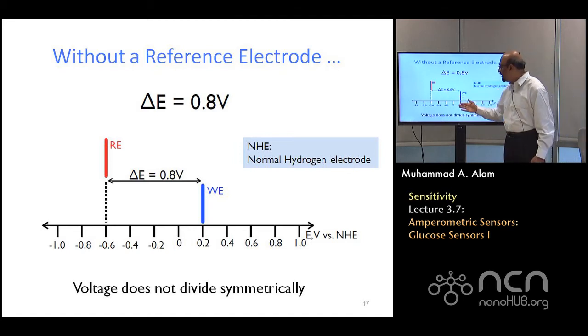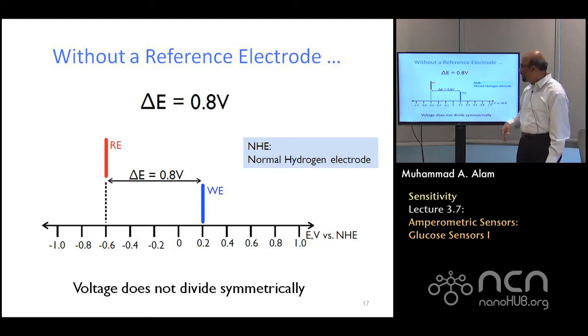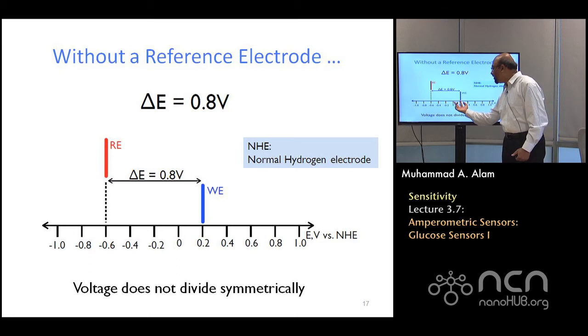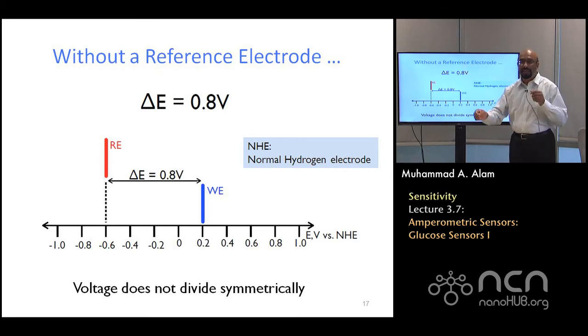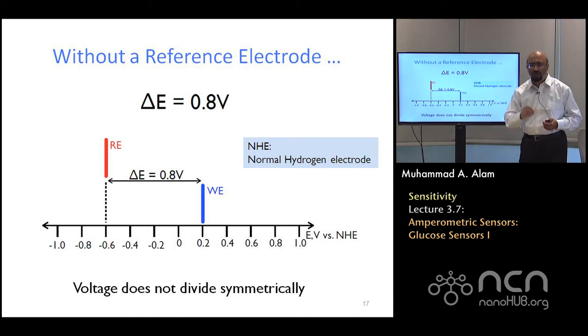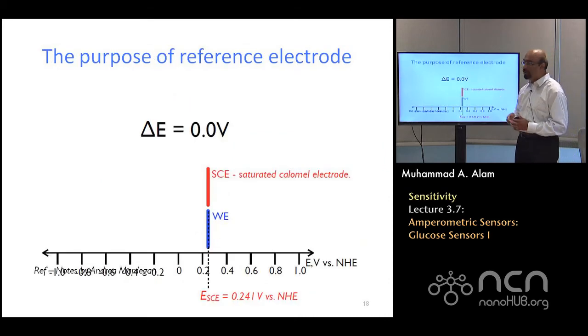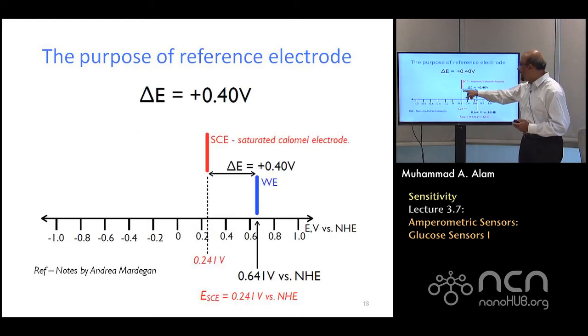The reason is that if, in this particular case, I apply 0.8 volts rather than 350 millivolts, then I cannot say a priori what fraction will get onto the working electrode and what fraction will get to the other electrode, the counter electrode. I cannot control the partition of the voltages. And if I cannot control it, then of course I may not have a controlled reaction. For every voltage, there will be slightly different reactions. So I have to do something about it. The way to do it is to insert a third electrode which maintains its potential at a given reference value, and then with respect to it you move things back and forth. The working electrode will then always have a fixed potential with respect to the reference electrode, and the reactions will be controlled reactions rather than arbitrary reactions depending on the exact configuration of the sensor itself.